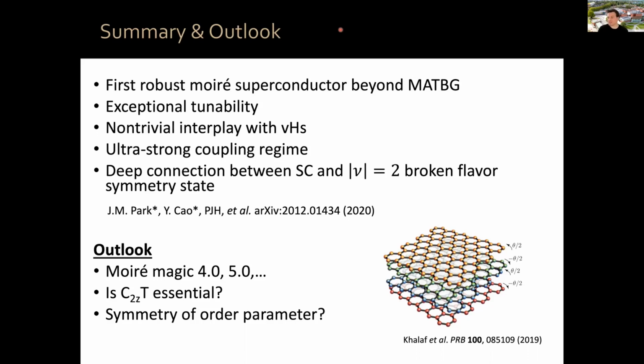I can imagine that the system exhibits a similar type of disorder as magic angle twisted bilayer graphene. There's probably some twist angle disorder, okay, in addition to chemical potential inhomogeneities, although it seems that those are weak in these structures. Twist angle disorder is probably a bit more dominant. I should mention that because the twist angle is larger, there is less relaxation and probably less disorder in the trilayer case. For this experiment we made 3 trilayer devices and all 3 were superconductors. So it was a 100% success yield, of course with a limited data set, but still, our yield for the bilayer case is about 50% in my group.